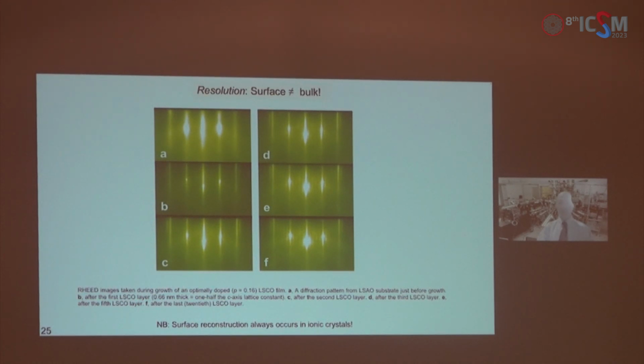So the surface is different from the bulk. And this is not a surprise. The opposite would be very surprising. In ionic crystals, like in cuprates, the cohesion energy is Madelung energy, which is very long range. We can feel it over 40 to 80 unit cells. An ion in the middle of the sample sees ions of opposite charge above, below, left, right, behind, and in front. But on the surface, half of that is missing.